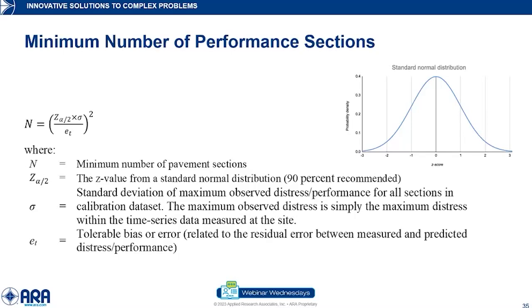Then there's also the standard deviation of the maximum observed distress for all sections in the calibration data set, which is, over the time history of, say, a single pavement section, whatever the maximum distress is of all those data points. Now, logically, you'd think it would normally be the last observation, because you expect distress to uniformly increase. Doesn't always work out that way. Sometimes, for whatever reason, some measurement error or something, it might have happened 1 or 2 years before your last observation, but that's what you're using here, and that's what you're figuring out the standard deviation for.